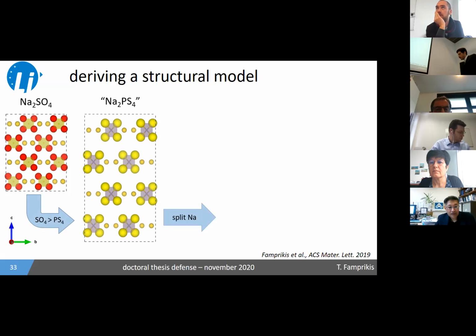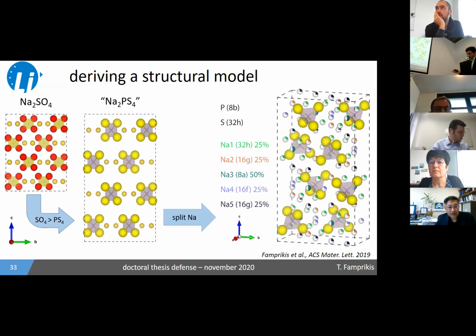So what we did is we performed DFT calculations to figure out where, energetically, the sodium would prefer to sit in such a structure. And what we actually found is that there are multiple sites in such a structure where sodium has very similar energies, and actually more sites than we have sodium atoms to fill them with. So we describe this with a disordered structure of multiple sodium positions partially occupied.